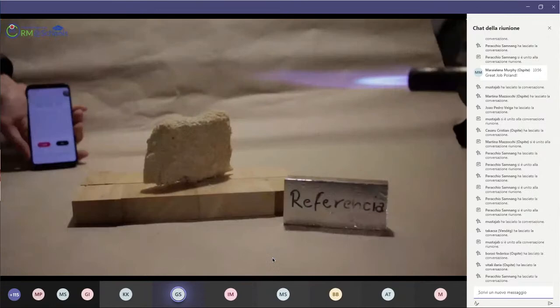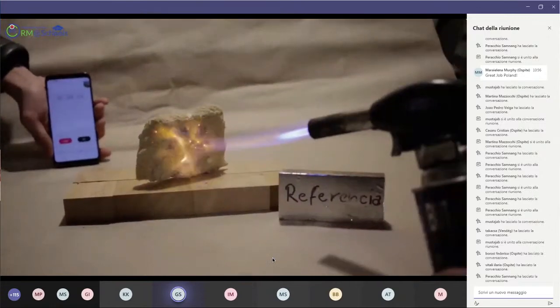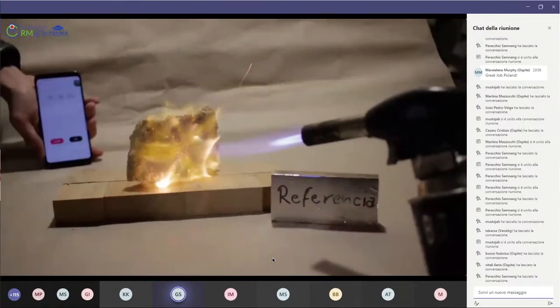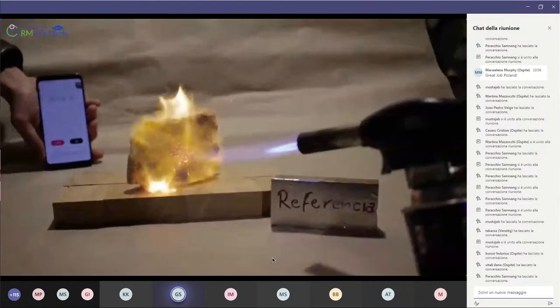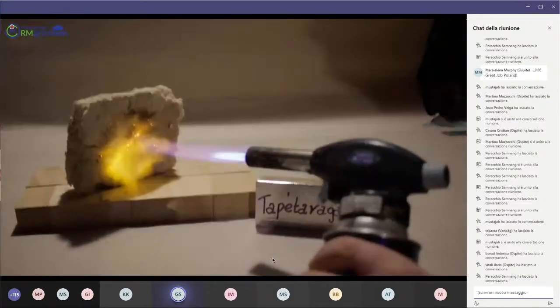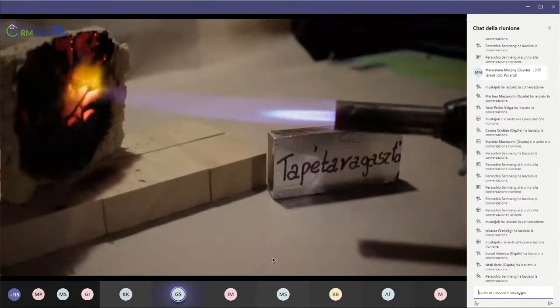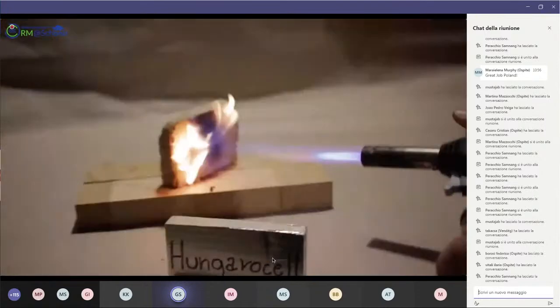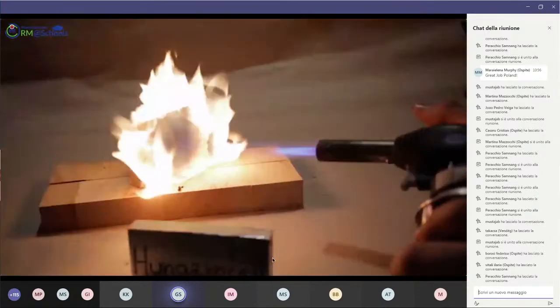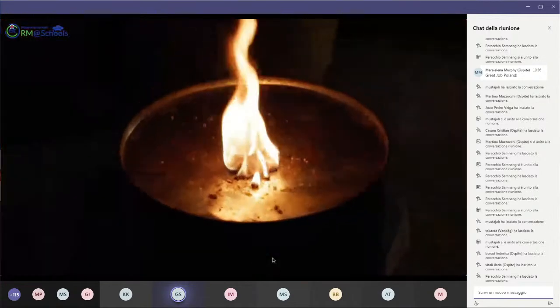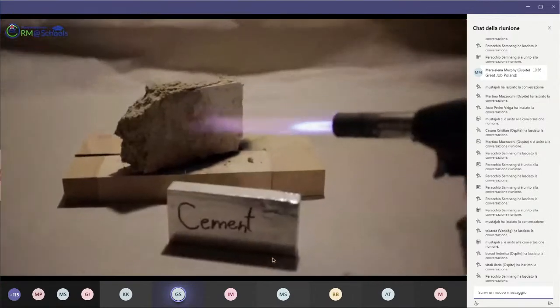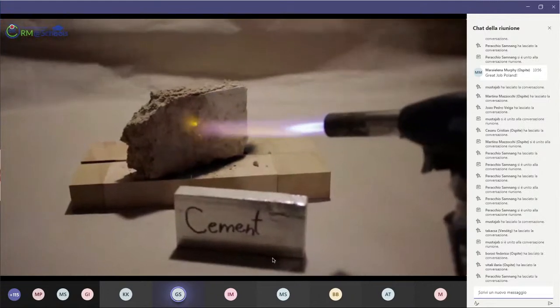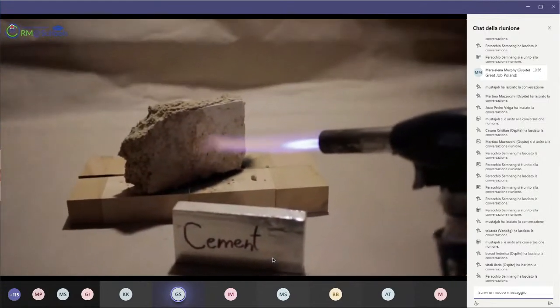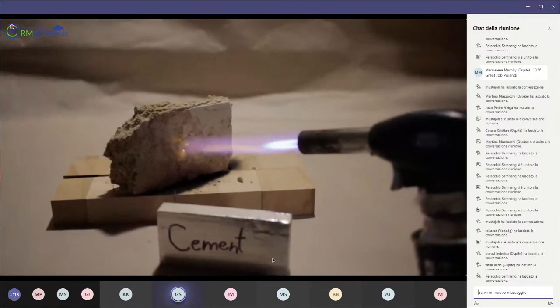In the first experiment, the reference material had difficulty withstanding the heat. In 1 minute and 34 seconds, the slab surface already doubled the room's temperature. The wallpaper adhesive sheet only increased by 1 degree Celsius after 2 minutes, making it a good thermal insulator. The polystyrene sheet warmed up in just 34 seconds and started burning. It turned out to be a bad thermal insulator. It's also flammable. The cement slab withstood the heat well, and the temperature did not rise at all on the other side. Also, the location of the flame was barely visible.